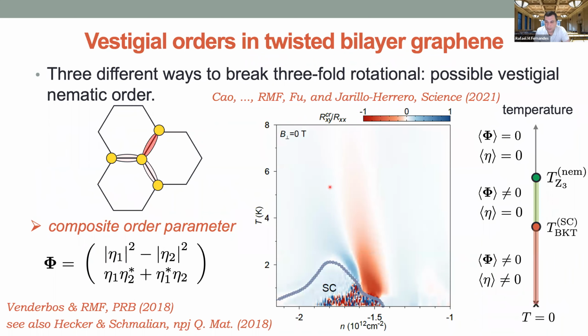Now I can apply again this idea of the vestigial phases. I have a superconducting phase that breaks gauge symmetry, but also breaks threefold rotational symmetry. The question is, can they be broken separately? You can do a calculation. The main difference now is that the composite order parameter is a 3-state Potts model, no longer Ising, and it can break at different temperatures.